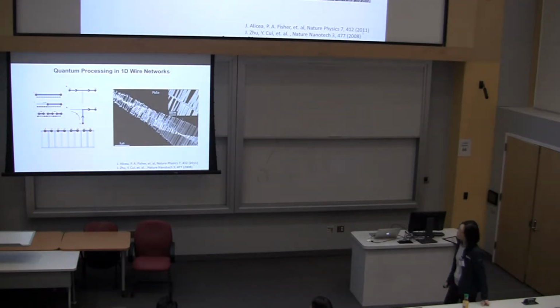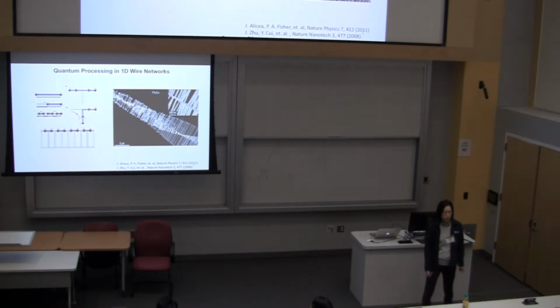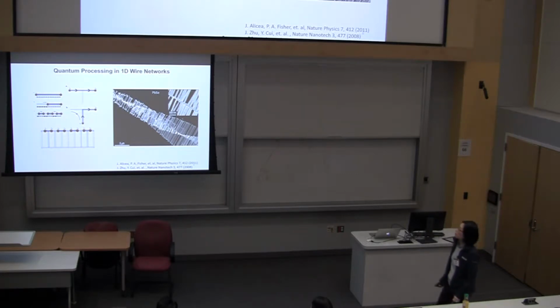Okay, so I think the killer app for studying nanostructures for topological materials is this, in my opinion, and that is quantum processing using 1D wire networks. So this is a theoretical framework that came out in 2011, where you have a topological superconductor in 1D confinement, right? And then all these gray boxes are local gates to locally control the chemical potential. And in this geometry, you'll get the Majorana bound states at the two ends. And by controlling the gates, you locally control where the Fermi level sits, and you can move it around. Okay, and the computation or the braiding of fermions is supposed to happen at these junctions.